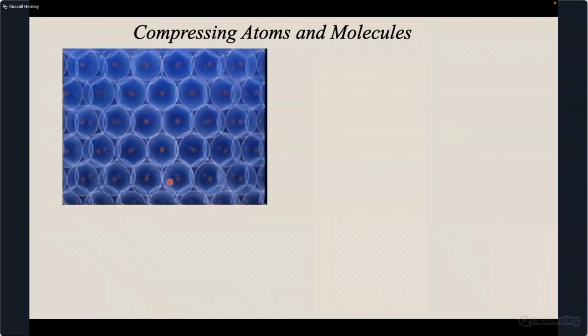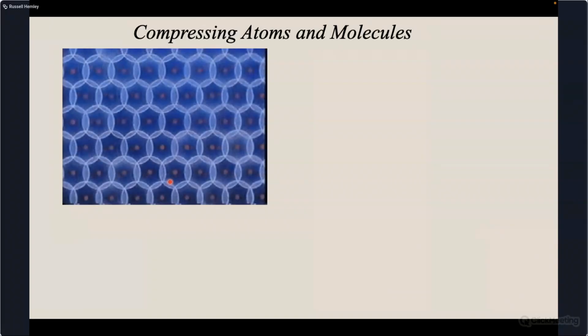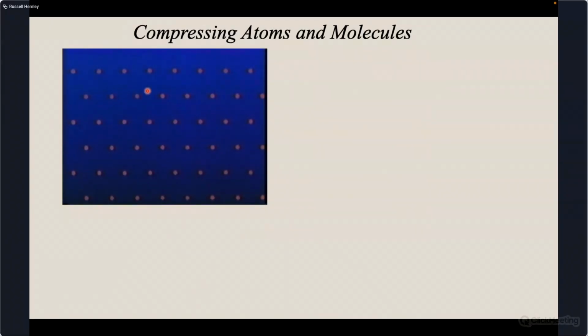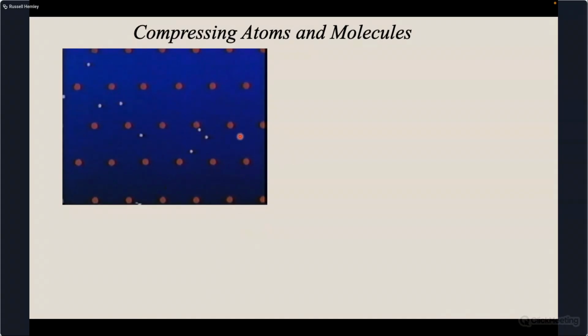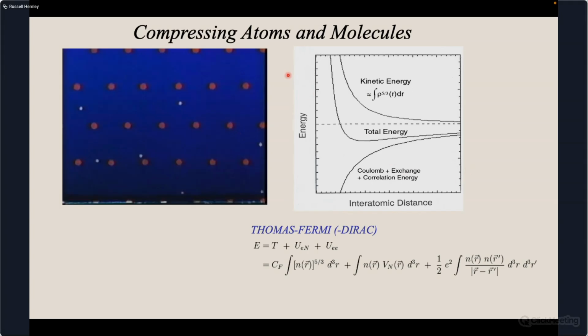So let's start at the beginning and give a little bit of historical perspective. What happens when we compress atoms? The conventional picture, shown in this simple model, is that when you compress atoms, you reach a condition where you no longer have the electrons stable in orbits around the ions, and instead you have a transition to a dense plasma state, and this arises essentially from the increase in the kinetic energy as you compress the atoms, using a very simple density functional kind of idea, Thomas-Fermi-Dirac, shown here.